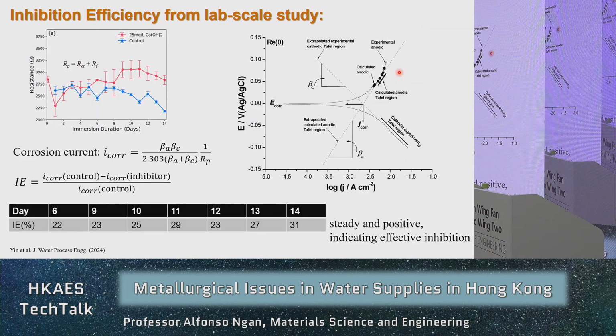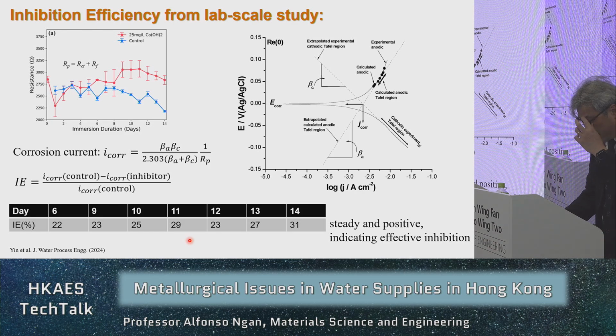So we also took the chance to recalculate this inhibition efficiency, not from the weight loss measurement now, but directly from the corrosion current, which could be related to the slopes of the anodic and cathodic branches, which are called Tafel slopes. So these are what these betas are. And then the calculated values are all in the range of 20-something percent to 30-something percent. And they are pretty steady. Again, they are positive, indicating that the chemical can protect the metal from corrosion.